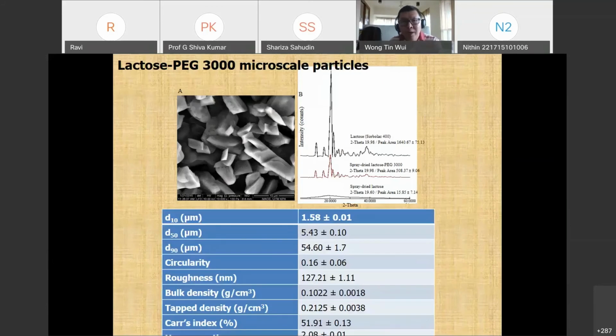And we also prepared our own microcarriers. Instead of using the commercial inhalation-grade lactose, we prepared our lactose microcarrier by incorporating polyethylene glycol 3000. This PEG 3000 is very important because it is waxy in nature. It can reduce the hygroscopic nature of the lactose particles. So the lactose PEG 3000 microparticles are only several micron in size. You can see the shape is definitely not round, it's a rock shape. And through XRD analysis, you realize that our spray-dried lactose PEG 3000 particle is rather crystalline compared to the pure spray-dried lactose. This will be good because it reduces the hygroscopicity, which may complicate our inhalation efficiency.